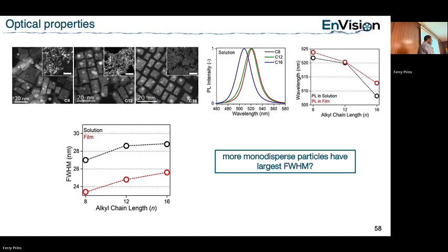So there's something funny here. If we really look at the full width at half maximum of the emission, we see that the more monodispersed particles, which are supposed to be better defined, actually have a broader full width at half maximum. This suggests that energetically they are actually less similar - here we have multiple band gaps, whereas in the other one we have a better-defined band gap, even though they're much more polydispersed.